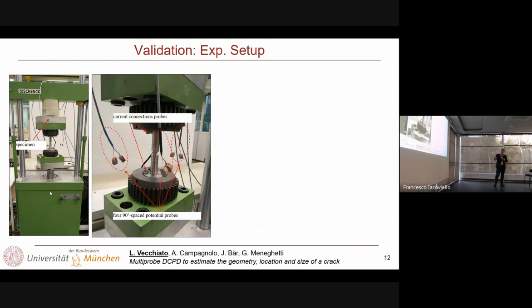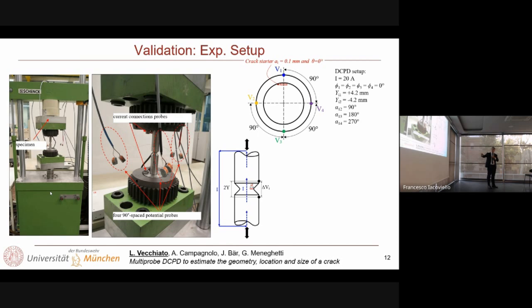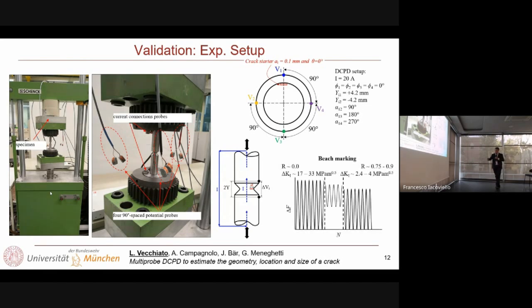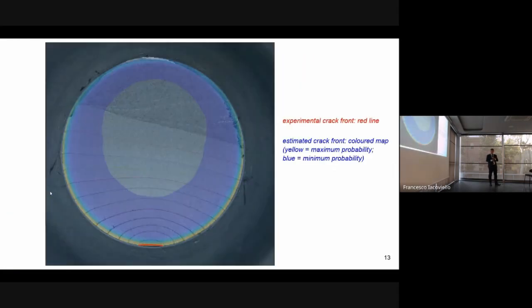This is an example of the experimental test, and this has been carried out on a hydraulic testing machine. Here, maybe you can't see the wires used to measure the potential drop since they are quite small, but they are copper wires of 0.1 millimeters. And we have chosen in this example to adopt 4 different potential drops located at 90 degrees from each other, with the actual position of each wire symmetrically located with the crack plane on the notch tip. To benchmark the crack front height change, the applied load has to keep almost constant the maximum K, and changing the load ratio to create different crack propagations or different roughness on the fracture surface, and then the possibility to finally measure the fracture surface image of the crack.